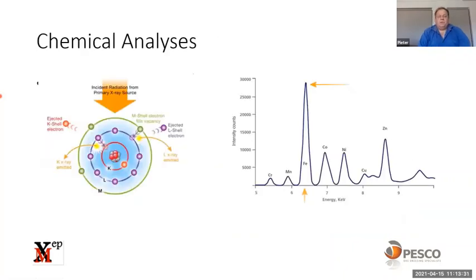Next step is chemical analysis. We're using XRF. So the sample is exposed to an X-ray beam where different energy levels are generated. We all use the X-rays in our labs to determine the percentage Fe, manganese in samples. Important for us to know is that the energy peak that's generated by the XRF will tell us what element it is. And then the intensity you pick up on that peak will tell you the quantity of that element in that sample. So if you have 60% Fe on this slide, it will give you a high intensity that's then referred to the percentage.